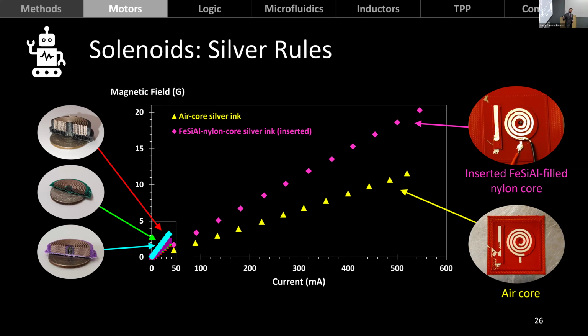In the case of the silver ink-based solenoids, the resistivity is much lower, so we are able to put more current through them and get higher magnetic fields. But they're still limited by the same phenomenon. And so we get 20 Gauss. How much is that? Is that good? Is that bad?